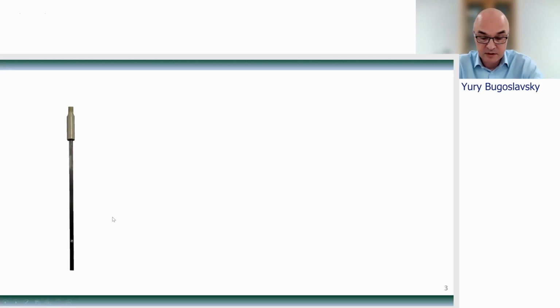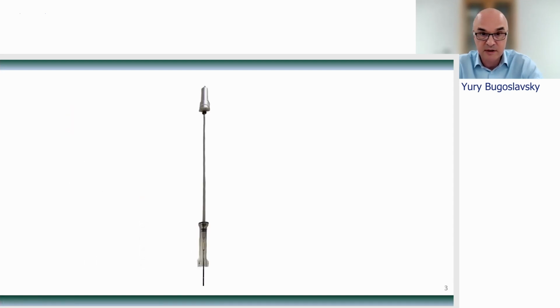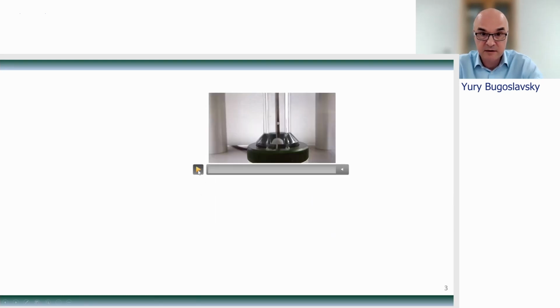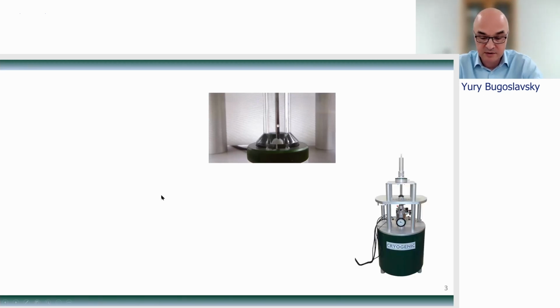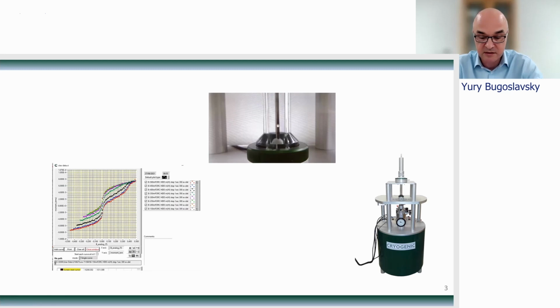When the sample is mounted, the sample holder is attached to the end of the vibrating shaft on the probe, like that. The probe is then moved into the load lock of the measurement system, and the sample is set to vibrate. I show a slow motion video of the vibration. The actual process happens at around 20 Hertz, but you can see the amplitude and how regular the vibration is. After that, the probe is loaded into the system in its working position, and after a few clicks of a mouse, you can see the data coming up on your screen.